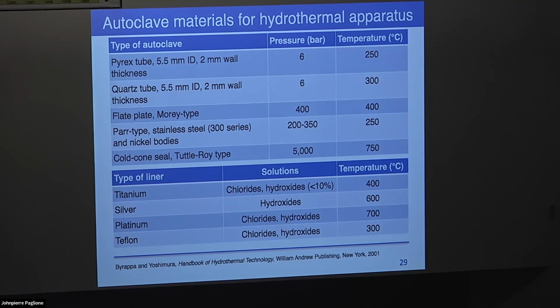And if you're not holding pressure, you're no longer doing hydrothermal synthesis, and all your water will evaporate off. So 250 is, I would say, a pretty good limit for hydrothermal synthesis using Teflon. If you do need to go to higher temperatures, or if you need to use different environments, you can use these different metals: titanium, silver, platinum, gold. Again, the big problem there is cost.